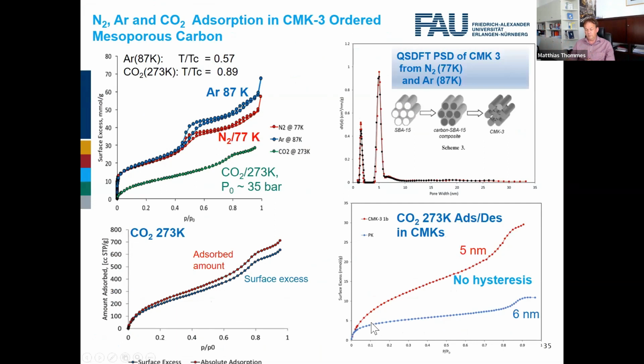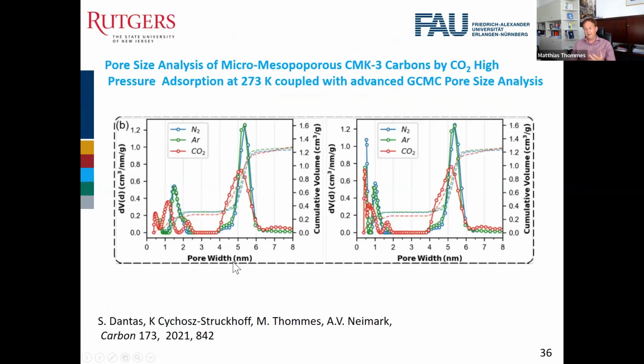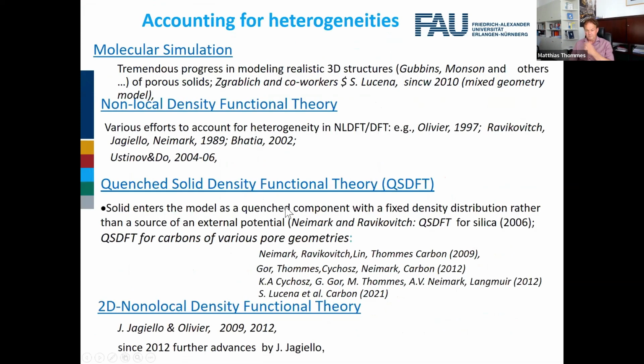We did experiments on model materials, again on CMK-3, and found some very interesting phenomena, such as that hysteresis would not appear over a large range, as I mentioned before. Of course, the complexity is also to measure surface excess. You have to convert these to adsorbed amounts to do some thermodynamics. But in the end, by applying advanced Monte Carlo simulation methods developed by Sylvain Dantas and Alex in cooperation with us, we could obtain pore size analysis from CO2 data, micro and mesopores, roughly up to 9 to 10 nanometers. Now, of course, this carbon story doesn't end there, when one has to look at the effect of heterogeneity.